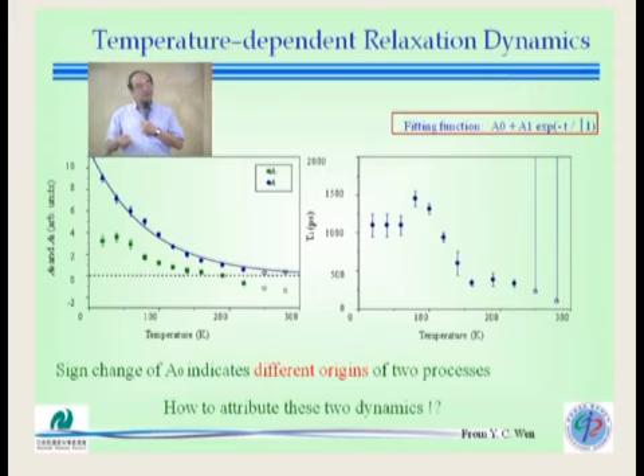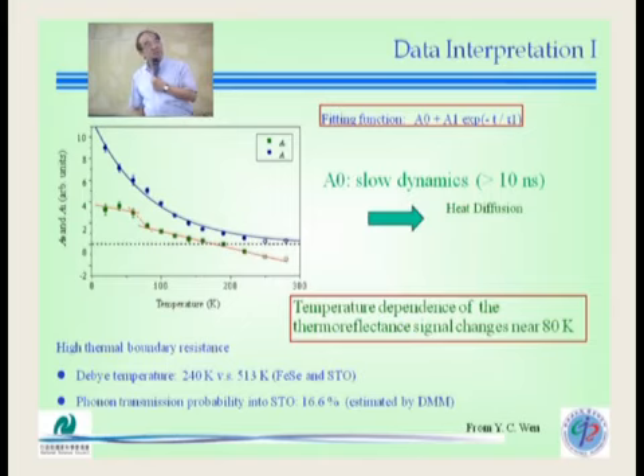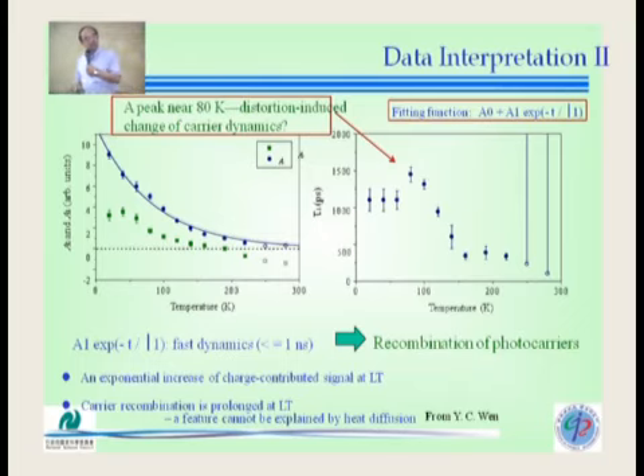And this kind of two-process dynamic, we need to understand. And as I mentioned, this A0 is the slow dynamic, and this indicates there is another temperature dependence of the thermoreflectance signal, and that is the recombination of the photocarrier. And so the structure change really gives you a very important phase dynamic difference here.